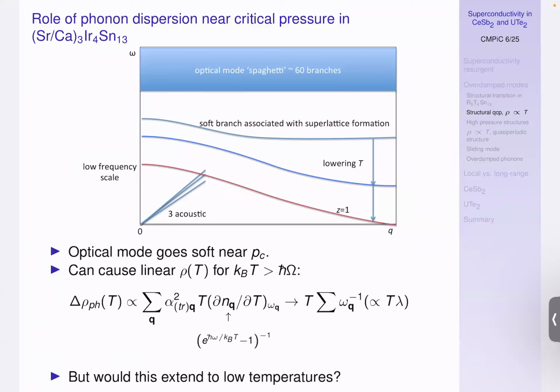And if this mode really has come down to low frequencies, then if one's temperature is above this scale, we should see a linear in temperature resistivity. And in fact, many metals have a linear in temperature resistivity once you get above about 80 Kelvin. You need to get to a significant fraction of the Debye temperature, which is usually around room temperature, right? So Debye temperature divided by 3, let's see. Then you start to see a linear in temperature resistivity. It's not unusual at all. It's happening in copper. But the funny thing is it's happening now at lower temperatures. So this temperature scale has been lowered.